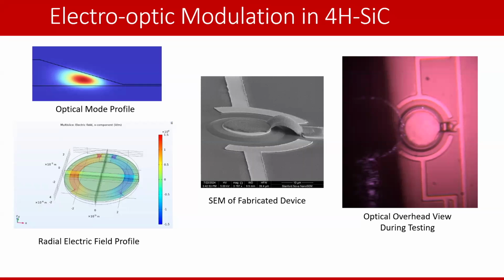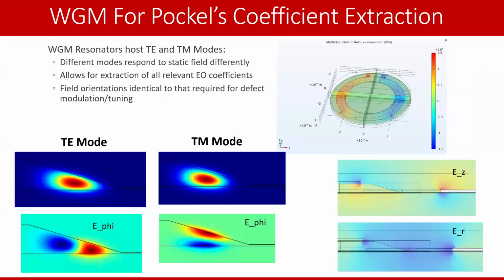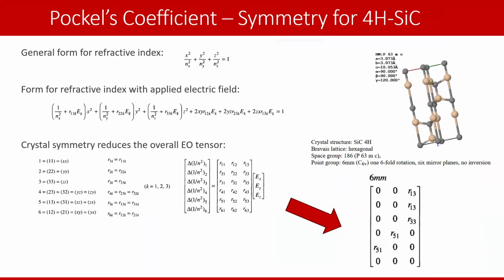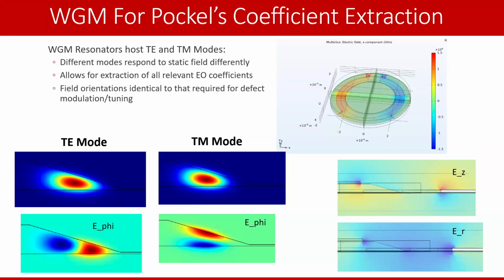What additionally adds complexity here is that if you look at this, there are both E_z and E_r components. And for others, there's another group at CMU, I believe, that's doing electro-optic tunability of 4H silicon carbide. They've built resonators and they've built modulators. They're very good, but they're only applying fields in the Z direction. And as I showed before on the Pockels coefficients, these are also in the X direction. So because of this waveguide and resonator geometry, you're applying fields in both the X and the Z direction, which adds a significant amount of complexity to exactly what's going on with the electro-optic shift.